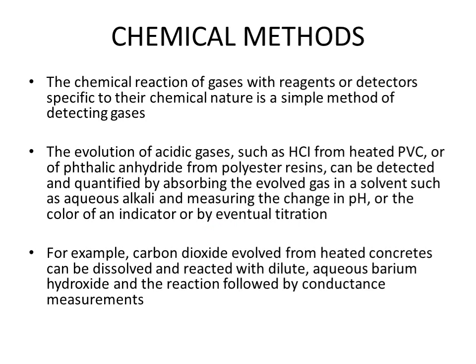Another example is carbon dioxide. CO₂ evolved from heated concretes can be dissolved and reacted with dilute aqueous barium hydroxide, and the reaction can be followed by conductance measurement. In this way, carbon dioxide is measured.